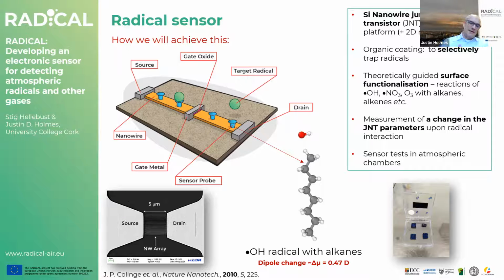The thing about these types of devices, the junctionless transistor, is that you can make these nanowires very small and increase their sensitivity. So what we then do is, we have these wires on the surface, and we put a functional group that can bind with the radical species on the surface. And when the radical reacts with this molecule or attaches to it, you generate a dipole moment. And this dipole moment is what we are detecting within the wire itself.